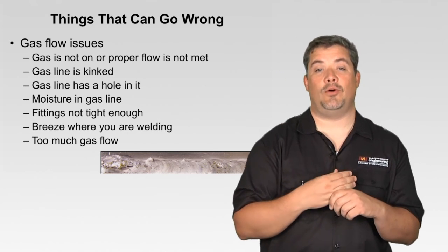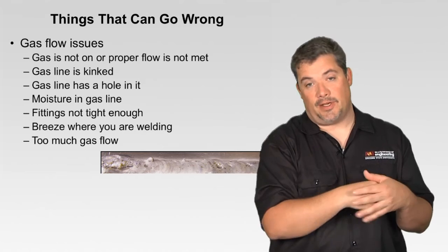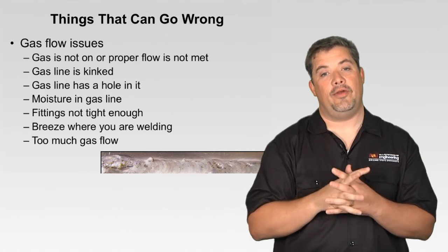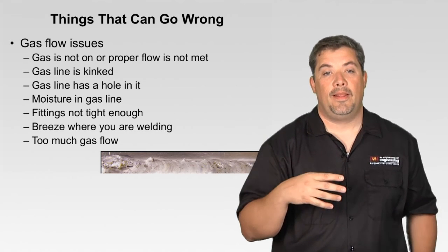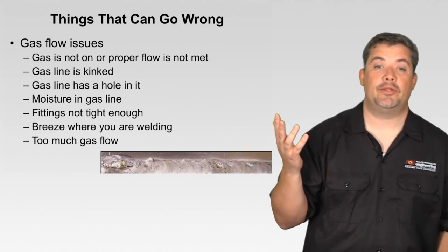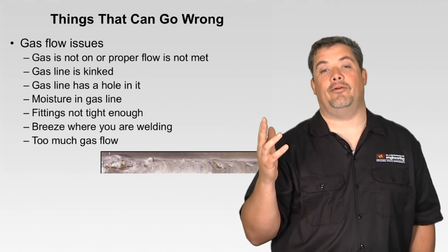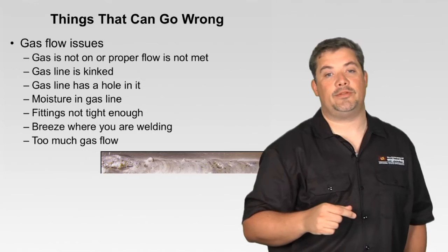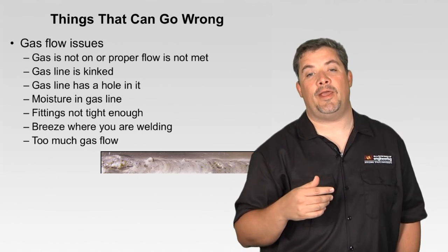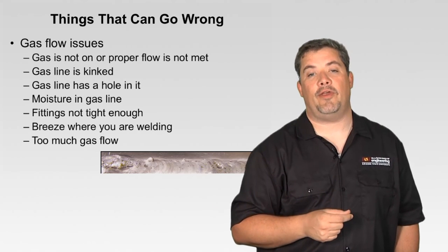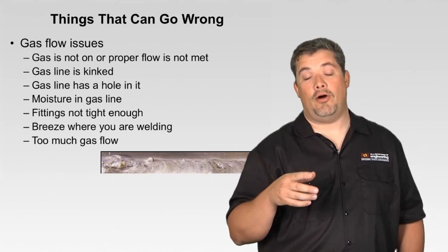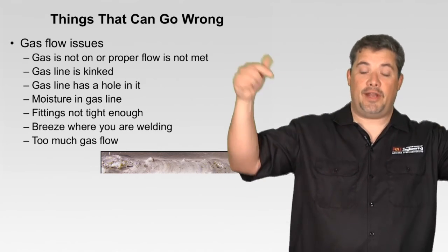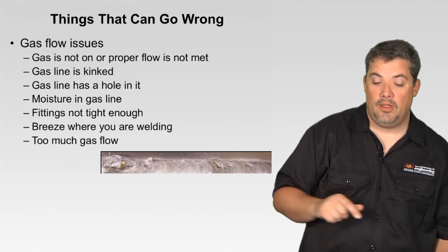Maybe your gas line has a hole in it, acts like a carburetor, sucks in atmospheric pressure, and now you have contamination coming in. Moisture in your gas line could happen too. Fittings aren't tight enough, therefore again drawing in atmosphere. Maybe there's a breeze where you're welding, or a fan. Got to be careful where that fan is blowing. Too much gas flow is also bad because it can create a Venturi effect and actually suck in atmosphere.